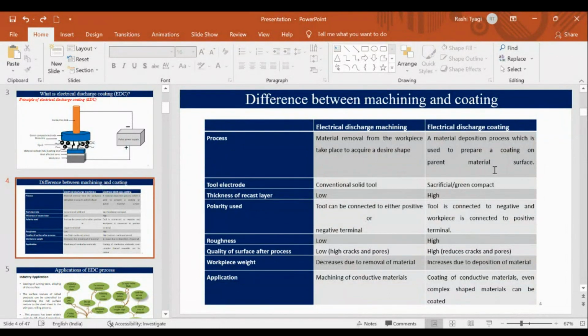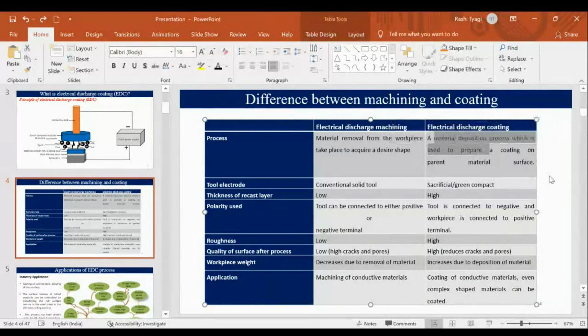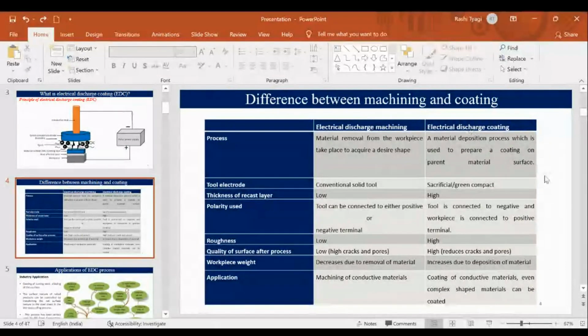But in the EDC process, if we are using soft powder, we can deposit the material on the workpiece surface, because we are making the green compact. There is a loose bonding between these particles. It will not do the machining operation, and it will do the coating operation. So this is electrical discharge coating.